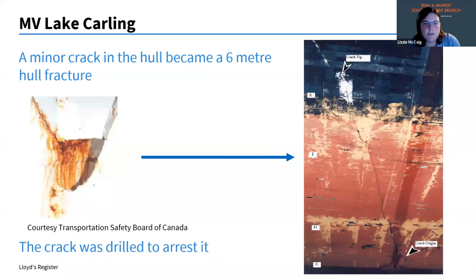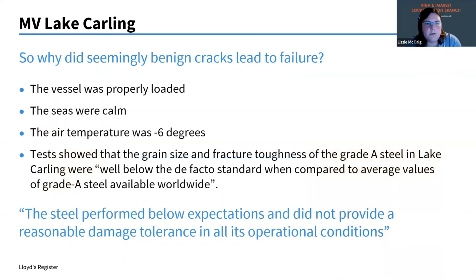And so the question was, why did it then lead to this massive 6-meter long hull fracture that they had to arrest by drilling a hole through it? So they'd looked at it. The vessel was properly loaded. The seas were calm. Temperature was only -6 degrees. It wasn't that cold. But when they looked at the material itself, they found that the fracture toughness and the